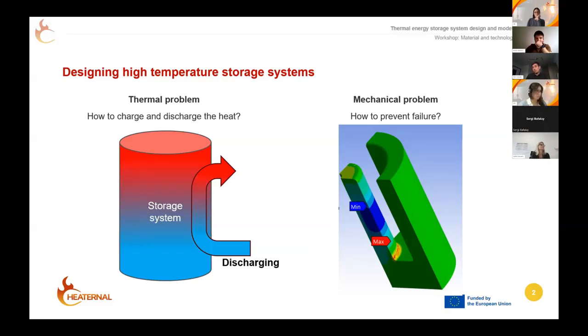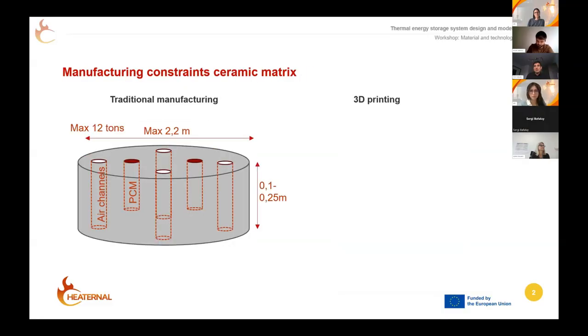You have a system which goes through thermal cycles, with rather large temperature differences, because we're doing storage at high temperatures, which usually also means high temperature differences. That means a lot of thermal tensions. They also have difference in thermal expansion between PCM and refractory. So you really need to pay attention to mechanical issues so that the system doesn't fail. So let's dive into how we can construct our system.